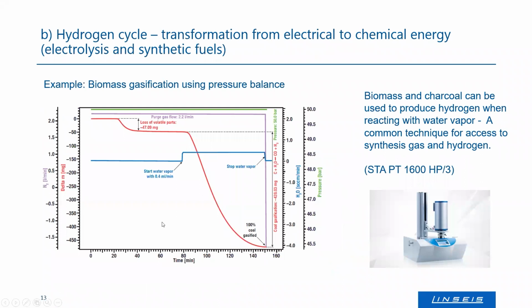And this process has been undergoing research for many, many years, because there are people who are trying to optimize that, to lower the temperature that's needed for gasification, to optimize the conditions of gasification. And that's where we already have a lot of experience, because we have a lot of customers who are buying our thermobalances, who are buying our machines to simulate that gasification process. So what we have is a machine, a thermobalance, that can be operated under pressure, that can be operated in steam atmosphere. You feed it with a small amount of your carbon-containing sample.